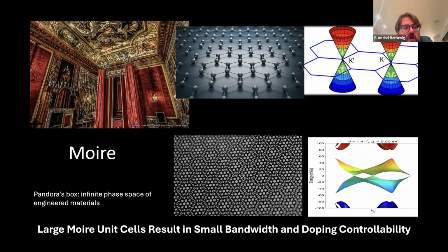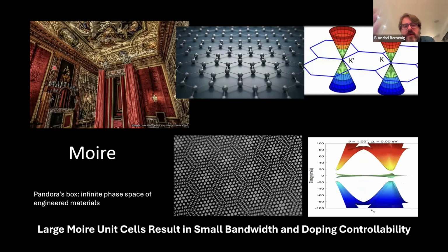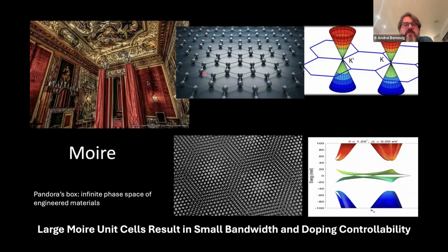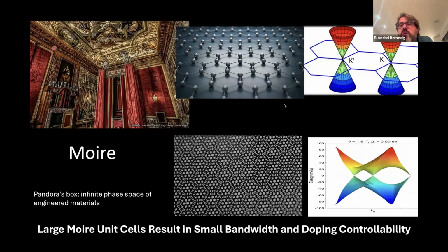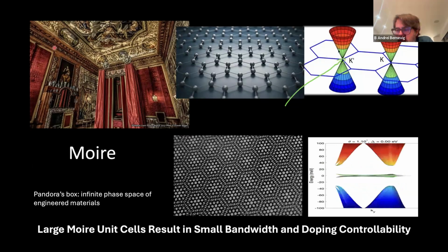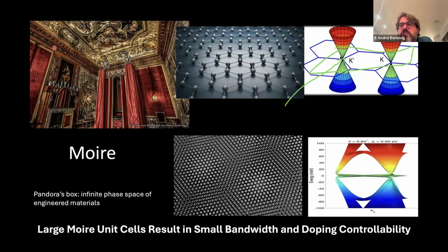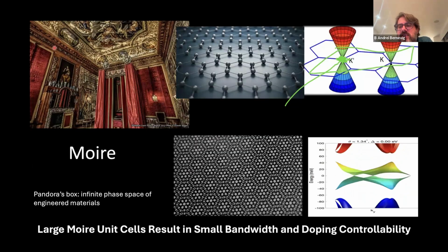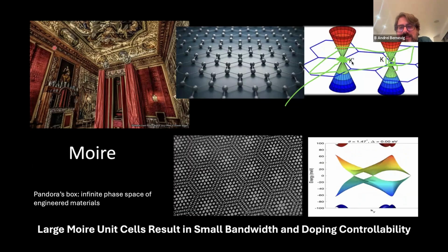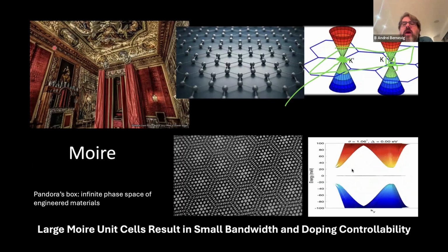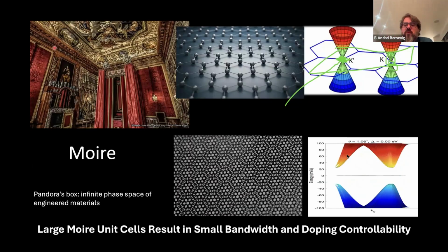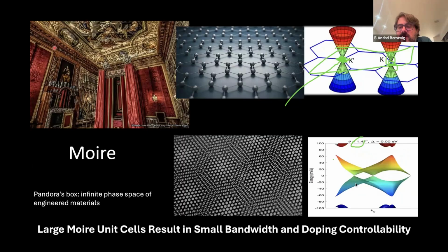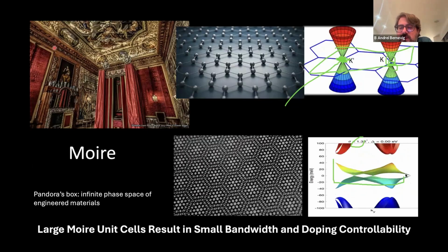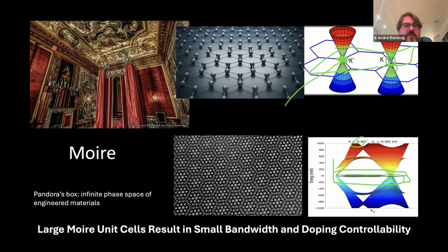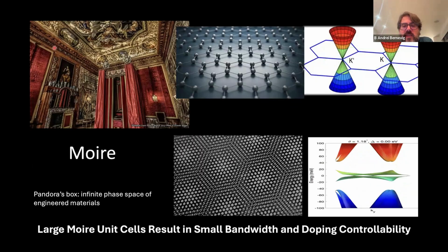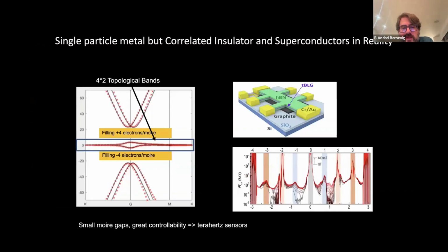In graphene, people have tried, Philip Kim, Efetov, many other people after them have tried for a long time to induce interactions in graphene. It's very hard to do because of this large dispersion, which means the density of states of electrons here, where the Fermi level is, is very low. But now, when I take these 2 layers and rotate them by 1 degree, because I have flat bands, so no kinetic energy, then interactions become important, and hopefully you can get interacting states of matter. And remarkably, this is the case.